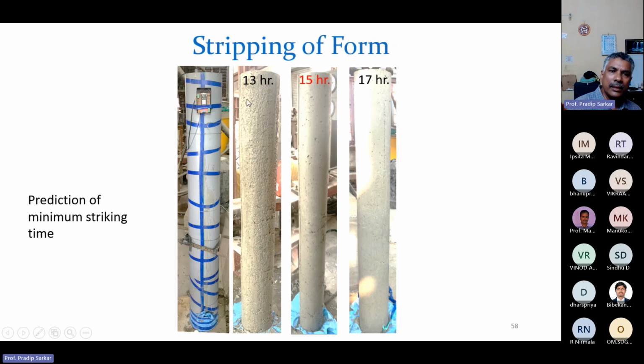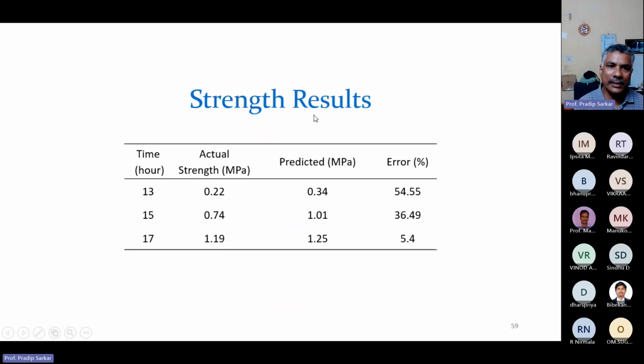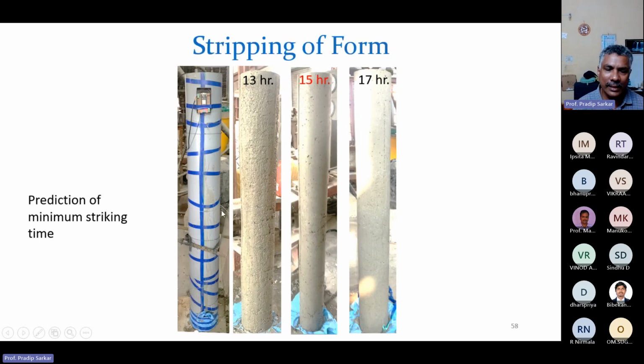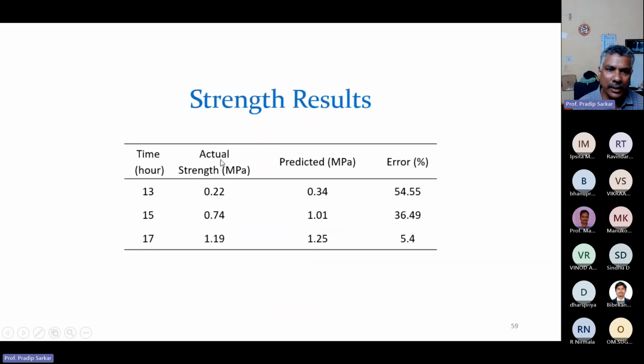And if you see the removal of the formwork, visually how the column looks. We removed the formwork at 13 hours for this column, 15 hours for this column, and 17 hours for this column. Now the actual strength results: we also had cube specimens of this same concrete, and at the same time when we removed the formwork, we took the cube strength. From the strength break test, we got compressive strength data of 0.22 megapascal, 0.74 megapascal, and 1.19 megapascal at 13 hours, 15 hours, and 17 hours.